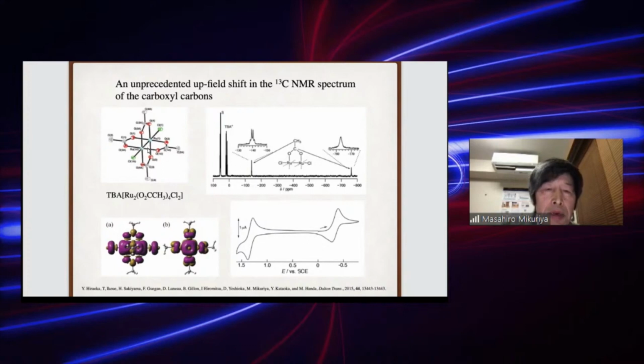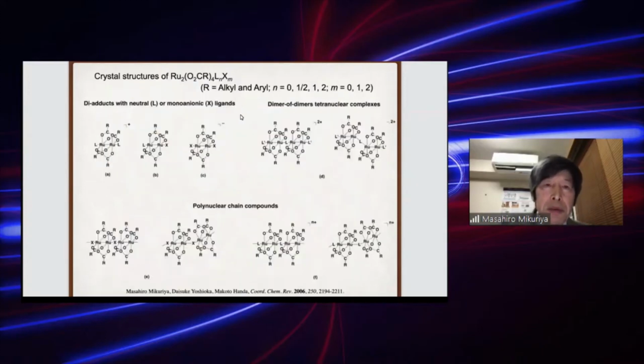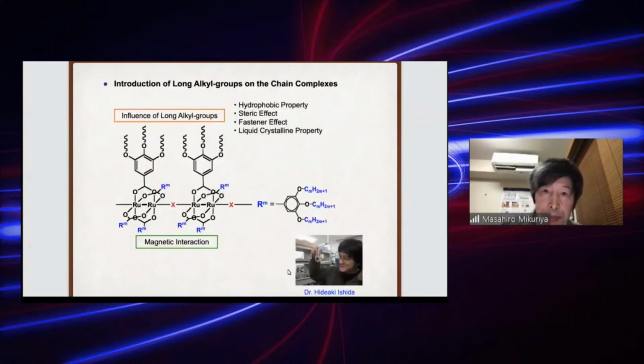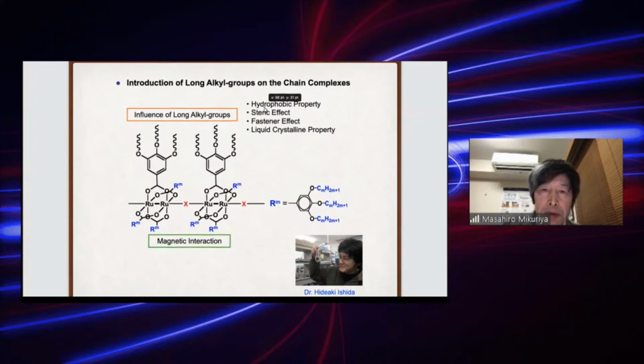This spin, the effect of this spin, we can see on the NMR spectra as a large upfield shift of carbon atoms. And this unit, we can make a chain compound by using this unit like this. If we add long alkyl groups to this unit, we can expect some hydrophobic property and liquid crystalline properties.